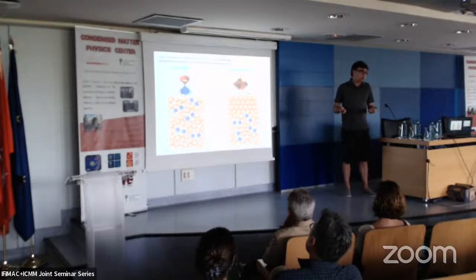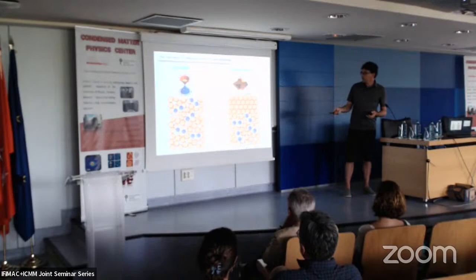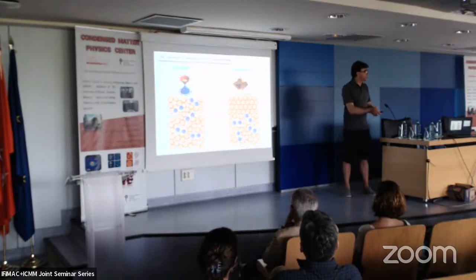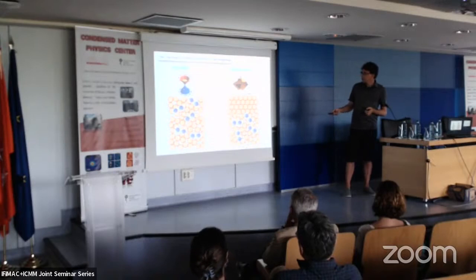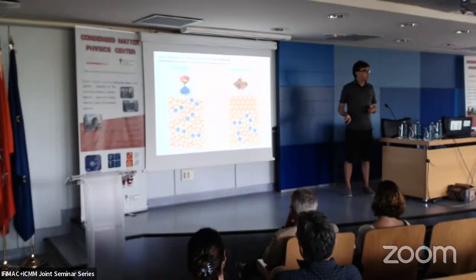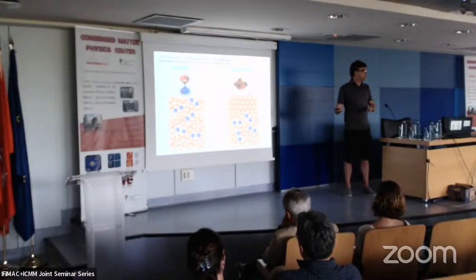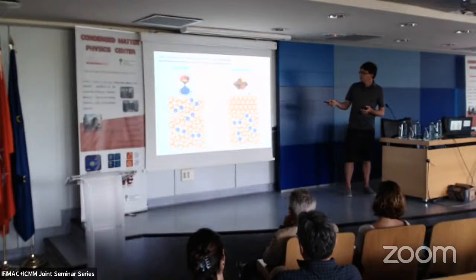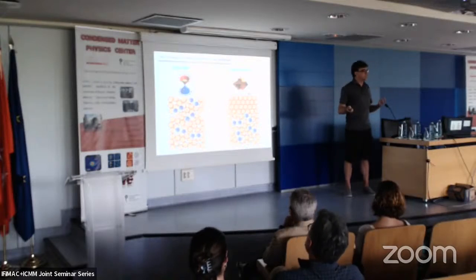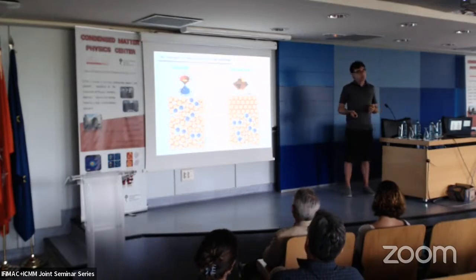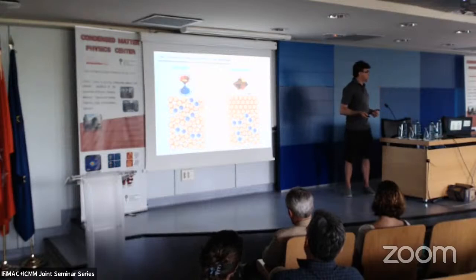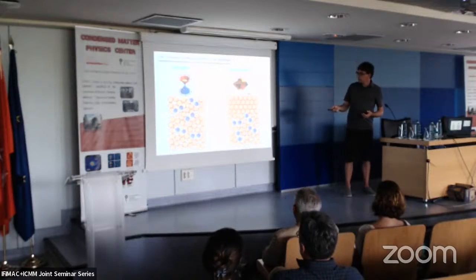And the second scenario is if we are not lucky with that, and this material is topologically trivial, then we still have this possibility that if we can combine the crystalline phase with the amorphous phase in this way, then by proximity, if this guy is topologically trivial, but still superconducting, by proximity we can induce superconductivity on the crystal phase. And the crystal phase, whether it is just bismuth or bismuth antimony, or whatever, is going to be topologically non-trivial. It's going to have surface states, it's going to have kink states, and you can have here for bismuth, etc. So maybe we can play the game of inducing by proximity superconductivity on the topological material. Okay? So conceptually, this is the most interesting case to me, but this one also might work, and this is part of the fun of this project.